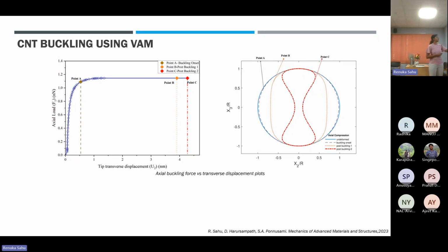Here you can see that a simple axial compression load was applied, and the beam up to some point, like point A, the behavior was linear. But after point A, where the buckling starts, you get a very huge transverse displacement even for a very small infinitesimal increase in the force. That means instability has occurred and the structure has buckled.